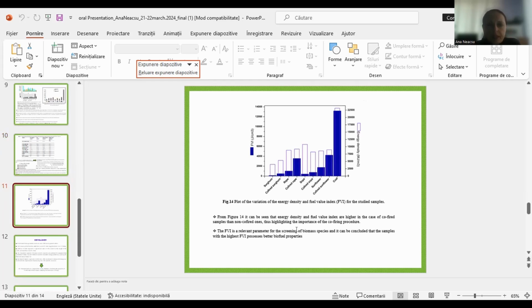From figure 14, it can be seen that energy density and fuel value index are higher in the case of co-fire samples than non-co-fire ones, thus highlighting the importance of the co-firing procedure.